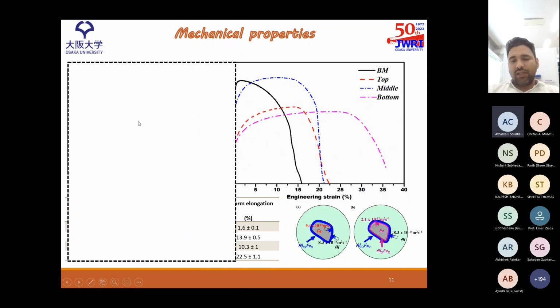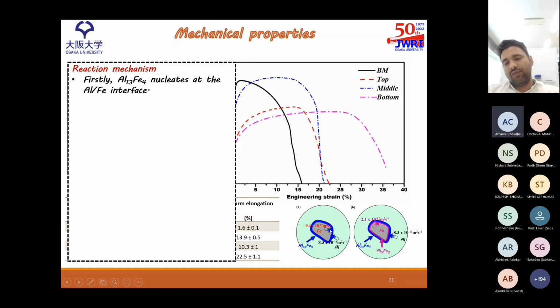Now coming to the reaction. So this is a Fe particle and this is aluminum. So what happens is the diffusion of iron and aluminum, and an Al13Fe4 layer is formed here. And since these are the rates of diffusion of iron and aluminum in the Al13Fe4 IMC layer, there will be a unidirectional diffusion of iron atoms into this layer, and the content of Fe keeps on increasing.